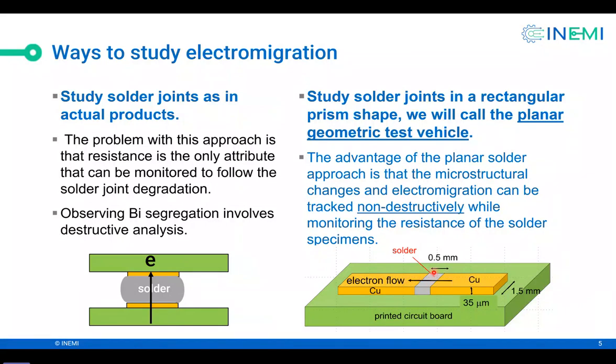So we can actually put this specimen under a microscope, and we can observe the bismuth atom moving from the right to the left and collecting at the left interface. While doing that, we can also measure the electrical resistance. So this is a very powerful technique of studying electromigration in tin bismuth solder.